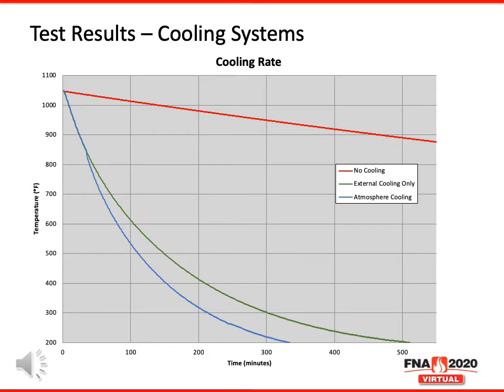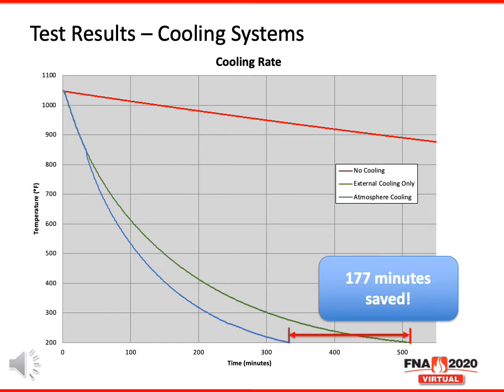Then the blue line, adding the atmospheric cooling system in addition to the external cooling system. So this would be recycling the nitrogen that's in the retort out through the heat exchanger and back into the retort again. And you can see, as I mentioned previously, there's a purge time that has to occur prior to allowing that heat exchanger to start. And then you can see where the blue line starts to split from the green line as the cooling rate increases once we're using the atmosphere cooling system. That gets us down now to about a 5.5 hour cooling time using both those systems. And so as you can see, there's about a 3-hour time savings by adding the atmosphere cooling in addition to the external cooling system.